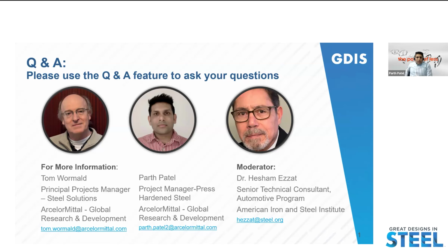I can take that. We have multiple thicknesses available across regions, depending on which region you're in and depending on the grade. For PHS, let's say for Usibor 1500, we have different gauges available in North America from 1 to 2.3. In other regions, it's different depending on the grade. If you're looking for Usibor 2000, we have 1 to 2 mil available right now. For Ductibor, we have different gauges too - it depends on your grade and your region.